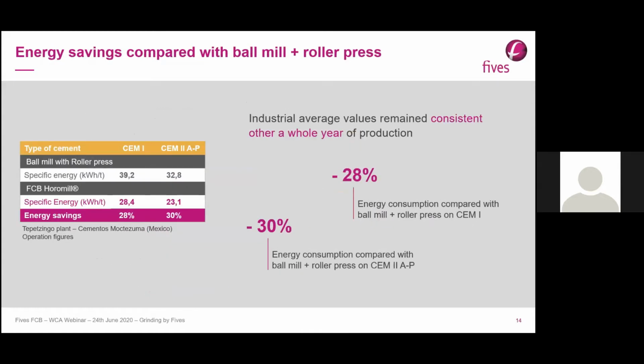Last, to finish the comparison, 2 figures to compare the energy savings in cement grinding, Horomill versus the coupled ball mill plus roller press. The saving is roughly 30%, 28% in case of Portland cement, 30% in case of pozzolanic cement.